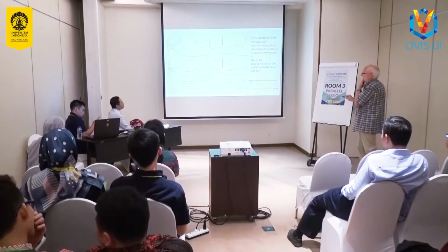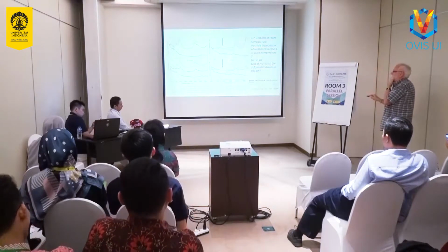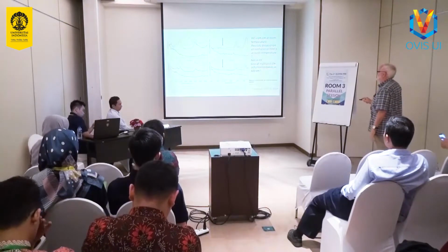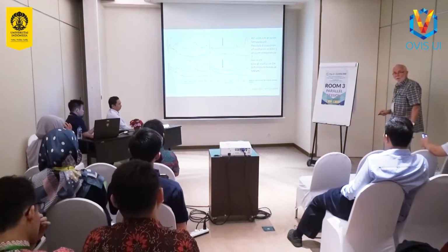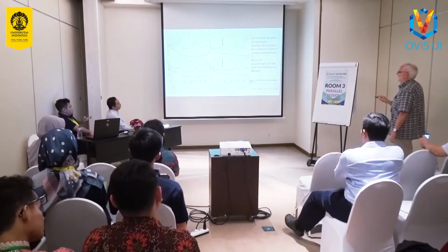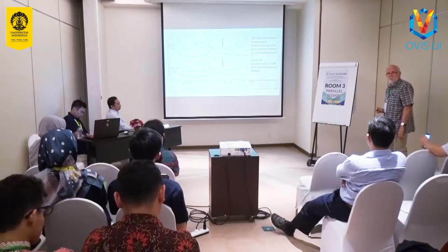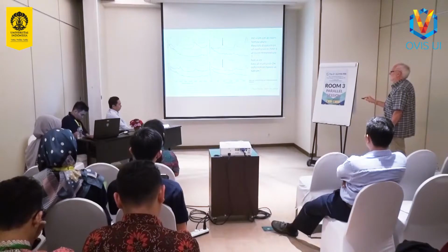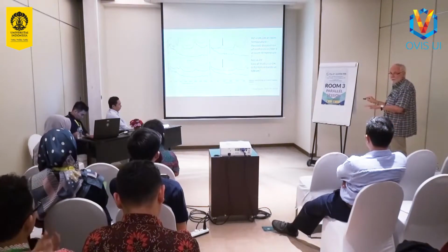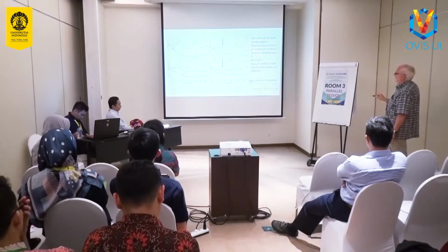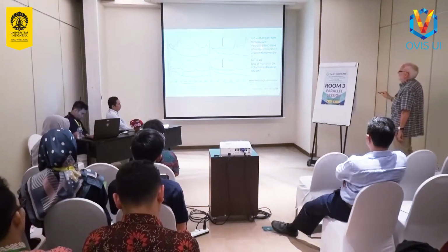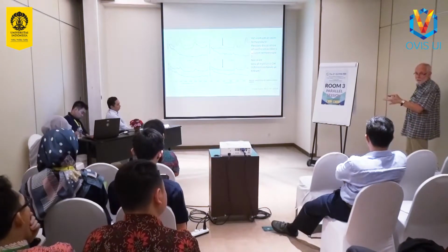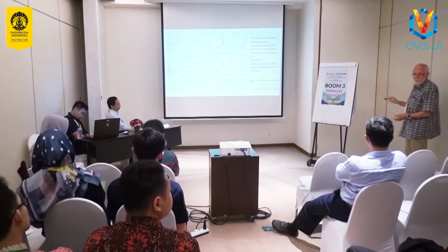Now there's two possible explanations for that. One is that in this zeolite the methanol is dissociated, so we've lost the OH bond. That was the interpretation preferred by the people who first did this experiment. The alternative interpretation is that the methanol is more strongly hydrogen bonded, so that the OH bending mode is broadened even further than it was here, and so it disappears into the noise. So that's still an open question. Is methanol in zeolite ZSM5 at room temperature dissociated or not? Now infrared spectroscopy says it isn't, since it's hydrogen bonded. Neutron says we're not sure.